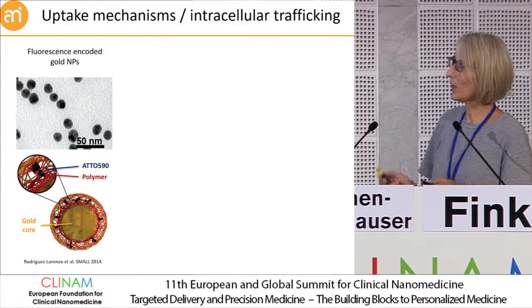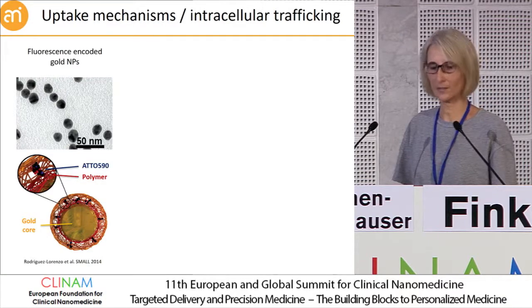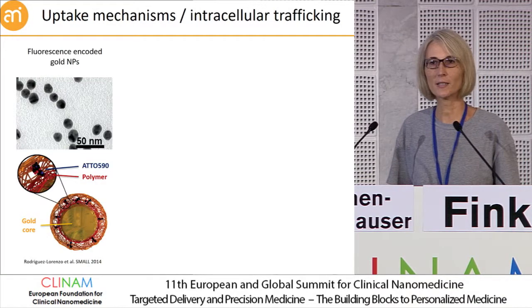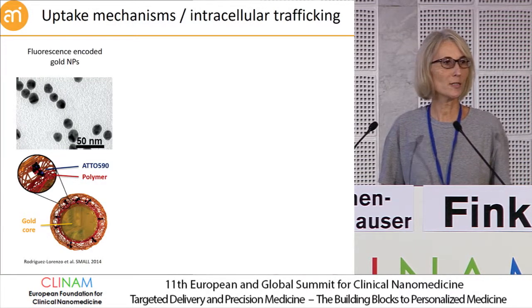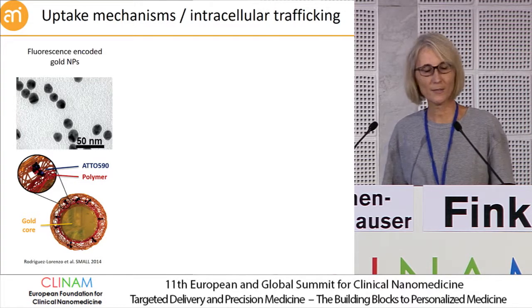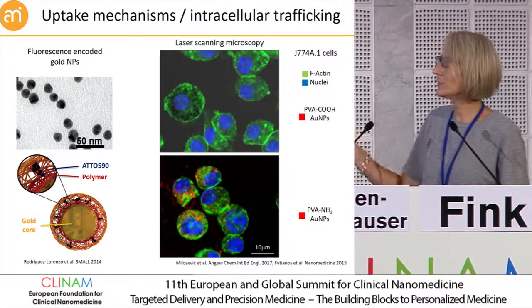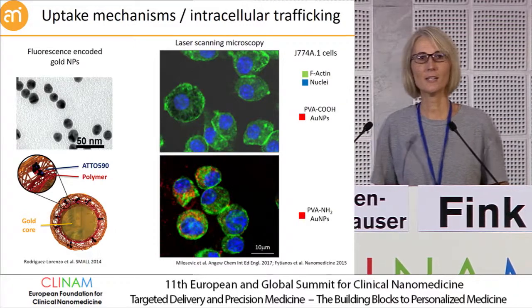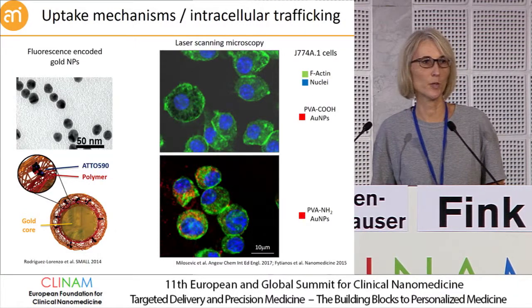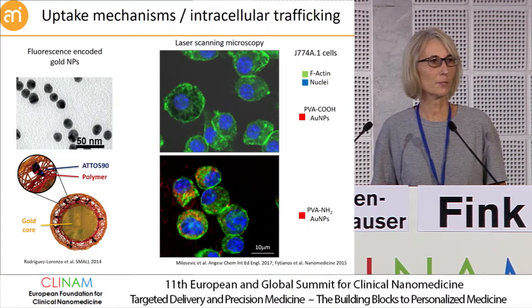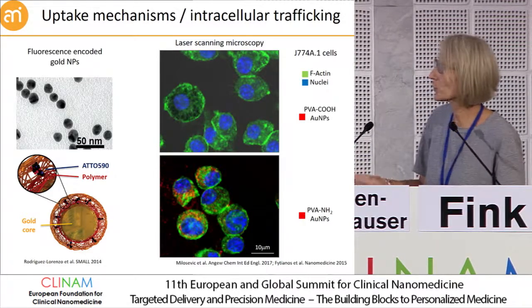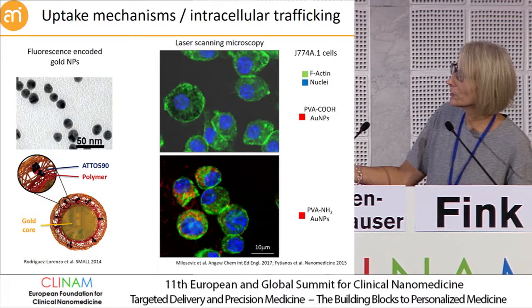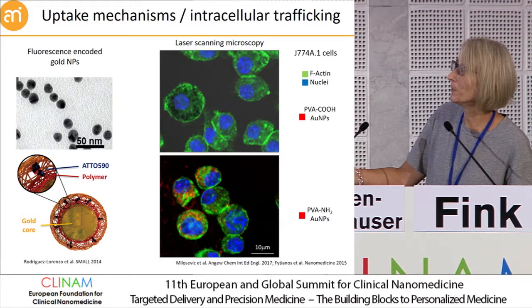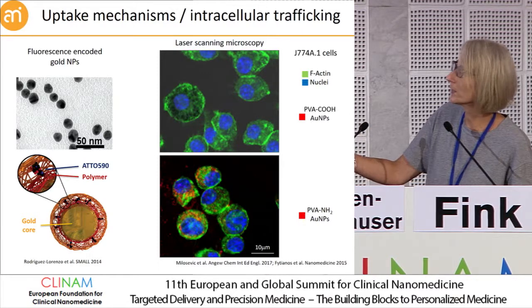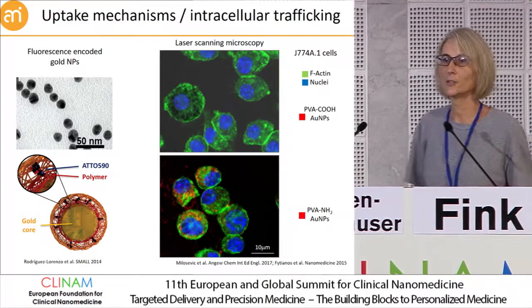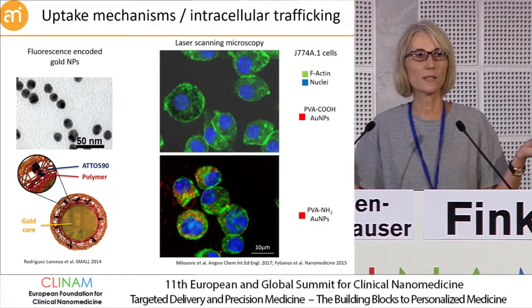because this can already change the interaction with cells. So after we worked out the synthesis for these particles, we tested positively charged polymers and negatively charged polymers, added this to the cell cultures, and the first step was to detect the particles by confocal laser scanning microscopy. So for the positively charged particles, we saw quite some uptake here, the red dots in the cells. However, for the negatively charged particles, we didn't see any particles.